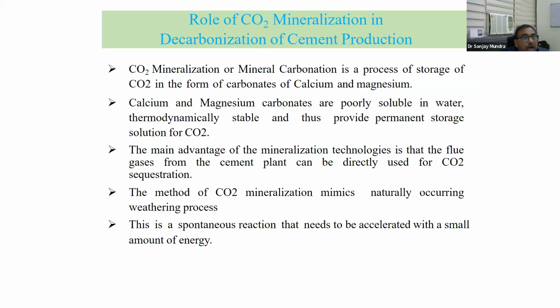Now, what is the role of CO2 mineralization in decarbonization of cement production? CO2 mineralization, or mineral carbonation, is the storage of CO2 in the form of carbonates of calcium and magnesium. As you know, different alternative aggregates have leaching of calcium and magnesium ions. So how can we trap this CO2 from your different plants? By increasing the CO2, we can convert it into calcite and magnesite. Calcium and magnesium carbonates are poorly soluble in water, thermodynamically stable, and thus provide a permanent storage solution of CO2.